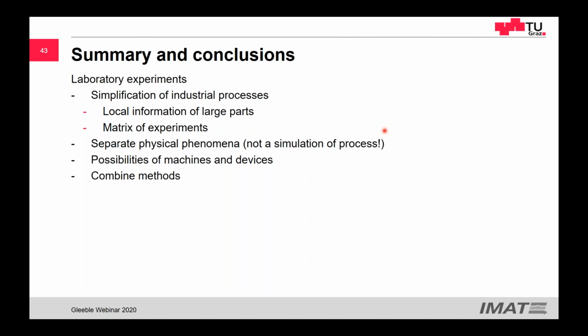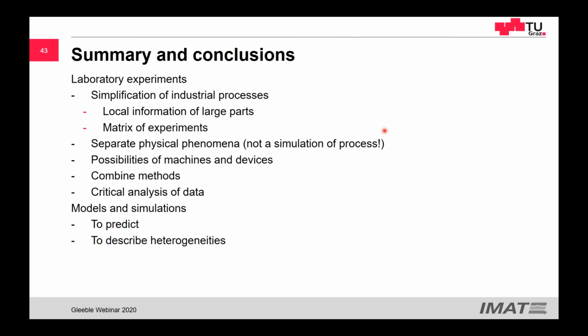And some of these methods are in situ, like synchrotron, but also scanning calorimetry or dilatometry. And some are just post-mortem, like metallography. There are, of course, some metallography that can be done in situ as well. We need to do a critical analysis of the data and of the method and compare and try to understand why we got what we got. And then we can use not only what we measured, but also what we understood from the experiments into models and simulation. What we cannot understand from the physical phenomena, we cannot model, and this is clear. And then we can use the models and simulations to predict, to interpolate, to describe heterogeneities, and so on.